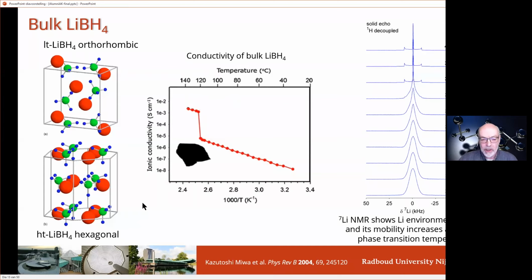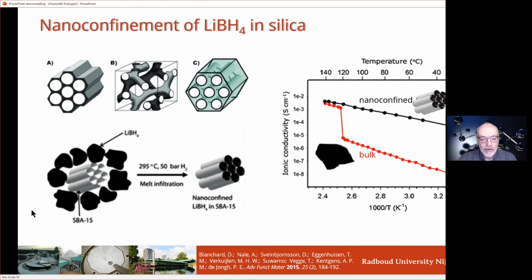So people have been looking at different approaches to mitigate that. One thing you can do is to nano-confine the material. Actually, that was a serendipity discovery that we made with our collaborators in Utrecht. They were working with nanostructuring of hydrides in carbon for hydrogen storage, and nano-confinement in carbon gave us very poor spectra. So we asked them, can't you do it in silica? They made samples specifically only to do NMR, to look at LiBH4 in confinement. But then at the same time, it came out that because of this, the lithium mobility and therefore the conductivity in the nano-confined material was very high over the entire temperature range. So that was a really interesting discovery.